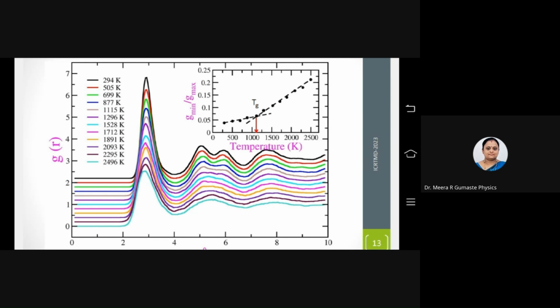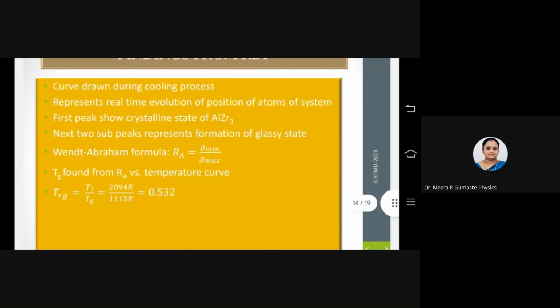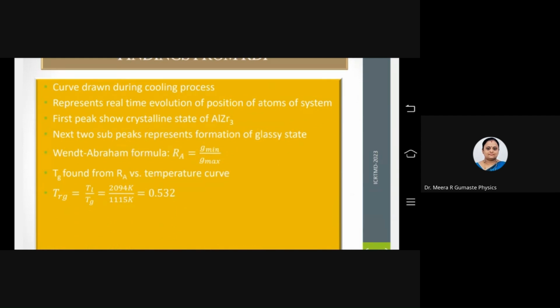So G min is the value of the first minima in the g(r) curve, and G max is the value of the first maxima in the g(r) curve. So that ratio versus the temperature I have plotted in the inset picture, and then took the slope, and that gives us the TG. So TL and TG both of them will give me this, known as the Wendt-Abraham formula. So that is RA. Okay, so RA is G min by G max, and that gives me TG.